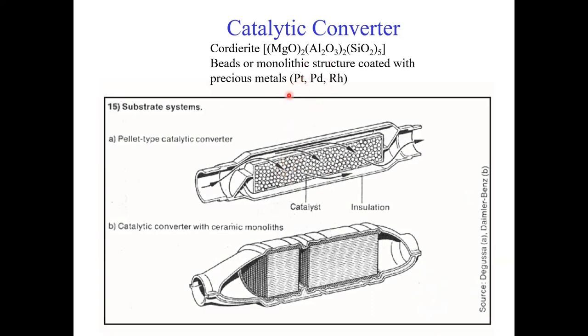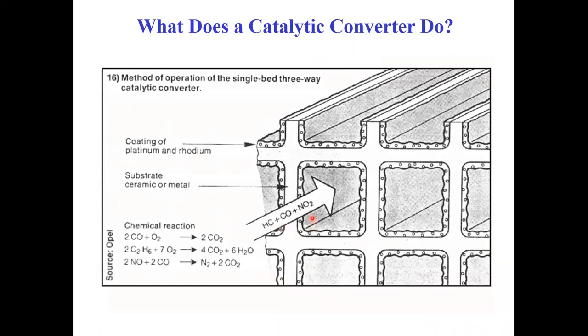The purpose of the catalyst is to promote reactions — for example, breaking up NOx into nitrogen and oxygen. The catalyst for the catalytic converter can also be in monolithic form, where you take a slurry material that can be shaped and extruded to drill holes through the green body. After firing, square holes are created. The gas flows through those holes, whose surfaces are coated with platinum, palladium, and rhodium catalyst, and the reactions are catalyzed by these agents. The catalytic converter further cleans the environment by decreasing polluting species.